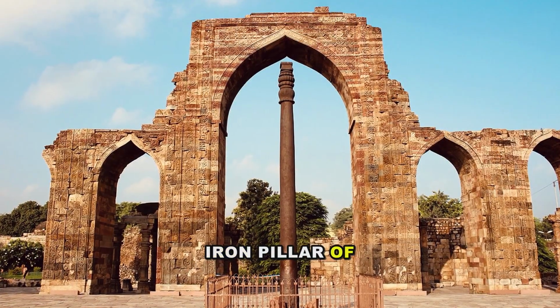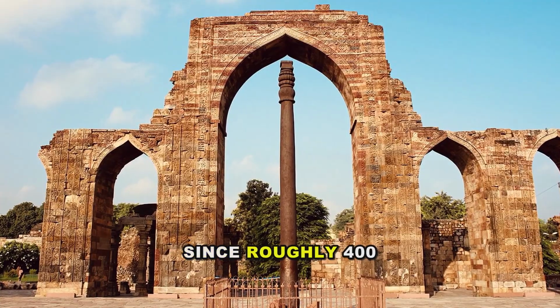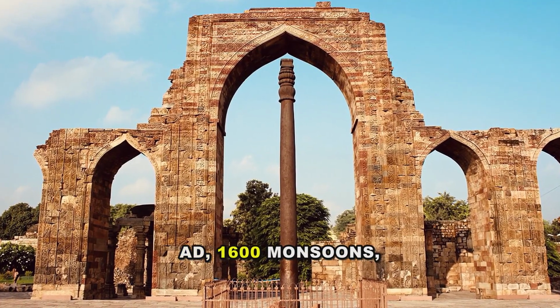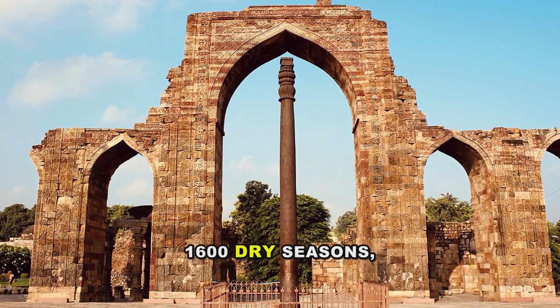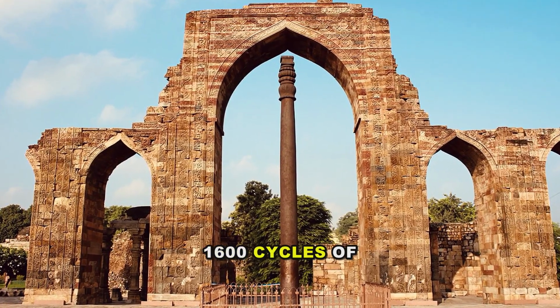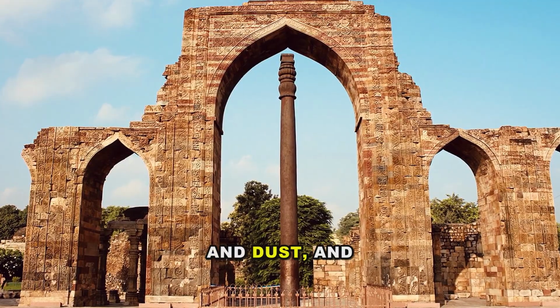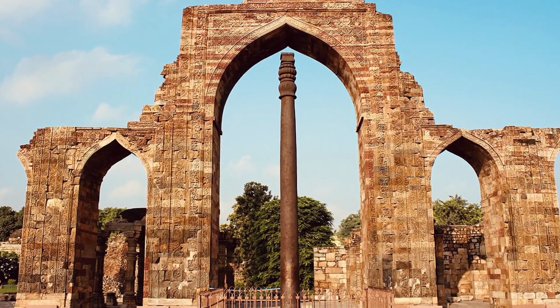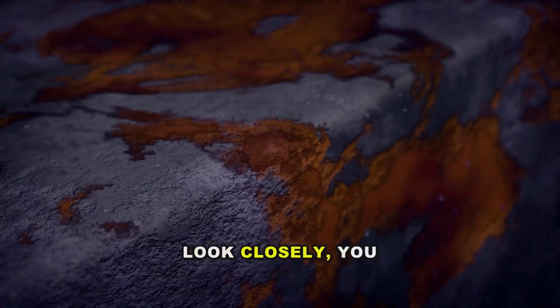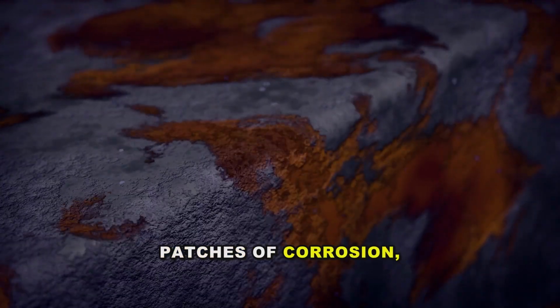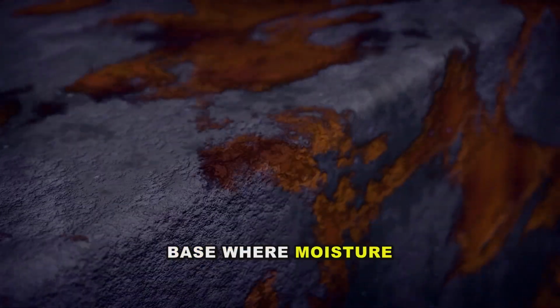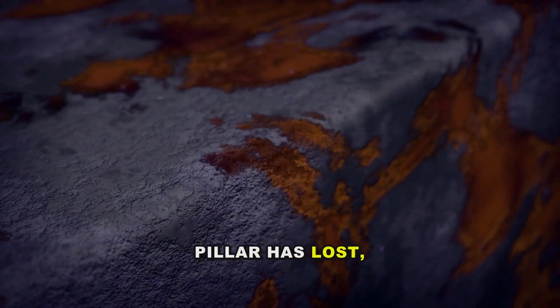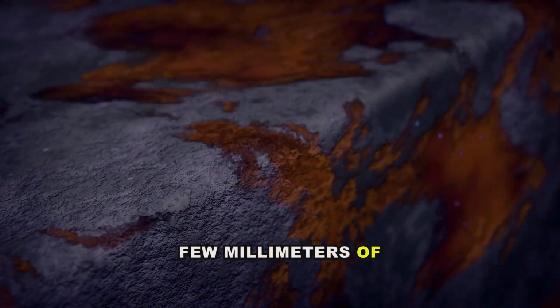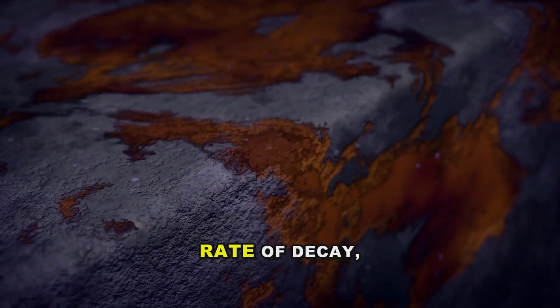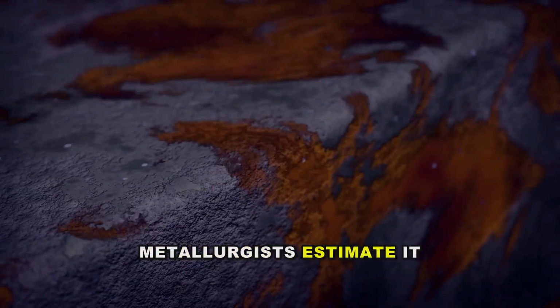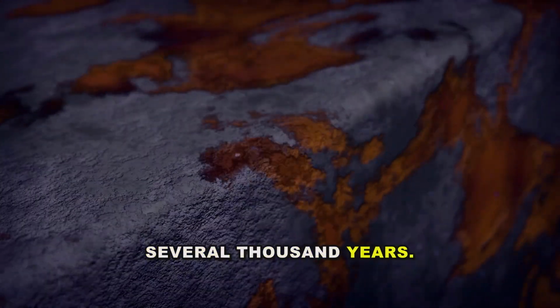The Iron Pillar of Delhi has stood in open air since roughly 400 AD, 1,600 monsoons, 1,600 dry seasons, 1,600 cycles of rain and heat and dust, and it is almost pristine. There is rust. If you look closely, you can see thin patches of corrosion, mostly near the base where moisture lingers. But the pillar has lost, at most, a few millimeters of its original thickness. At the current rate of decay, metallurgists estimate it could stand for several thousand more years.